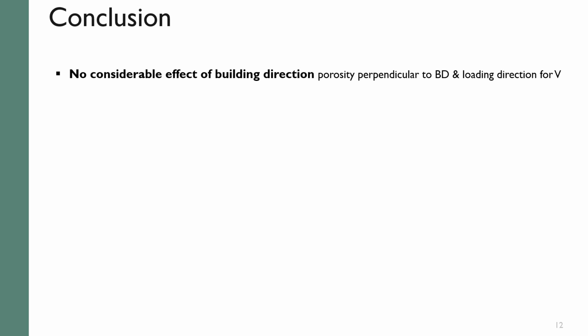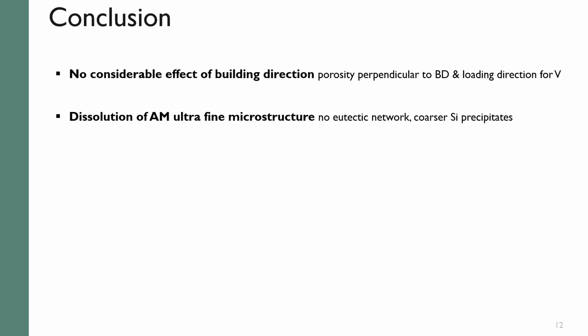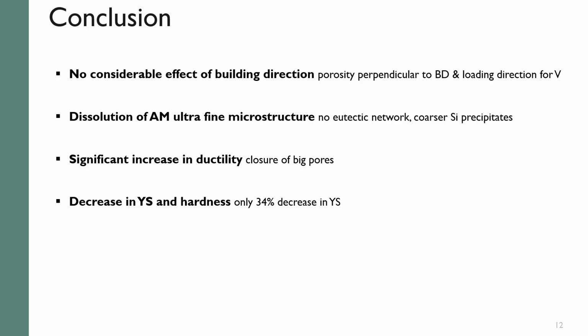And as for the effect of HIP, after the treatment, dissolution of AM ultrafine microstructure was observed, the eutectic network disappeared, and coarser silicon precipitates were there. Ductility increased significantly thanks to the closure of big pores. Decrease in yield strength and hardness was recorded, but the decrease in yield strength was limited to 34% only.